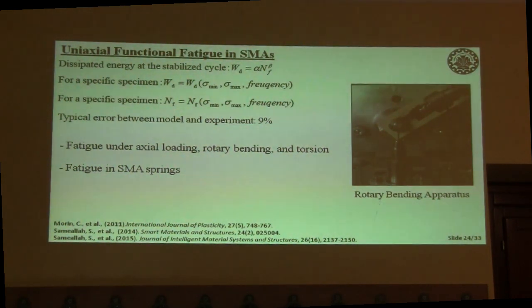Meaning that in the initial stage of loading, when shakedown is achieved, I can obtain the observed dissipated energy. Using this relationship, I can predict life cycle, number of cycles to fracture, in terms of, for example, minimum stress, maximum stress, and frequency of the applied loading. In our numerical simulations, we have at most 9% error, which is reasonable to predict life cycle of a shape memory alloy.